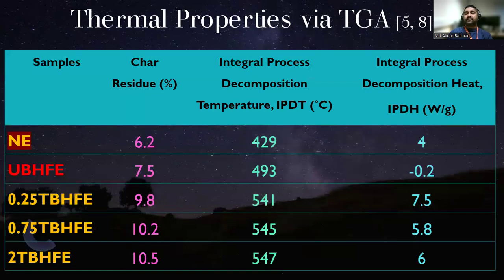I did not include any graph over here, but rather included the whole result. So when we use the NE, meaning neat epoxy, the char residue is around 6.2%. Similarly, the IPDT is 429. However, when we did the untreated one, it becomes 7.5. The interesting part is the IPDH value is negative.